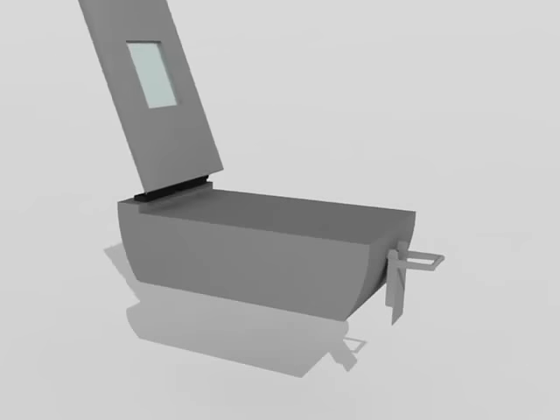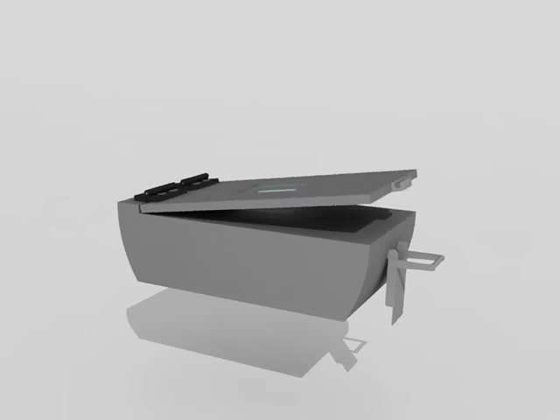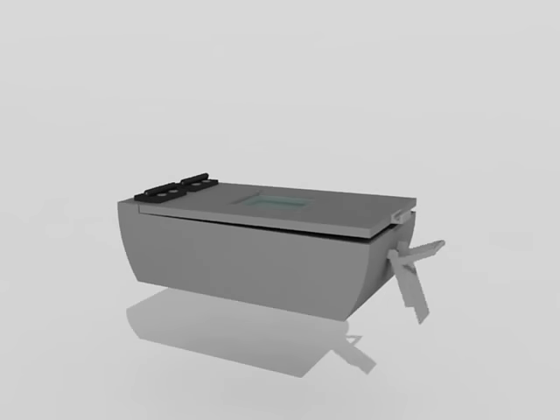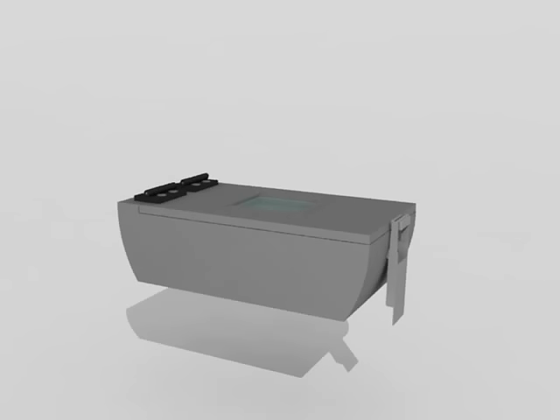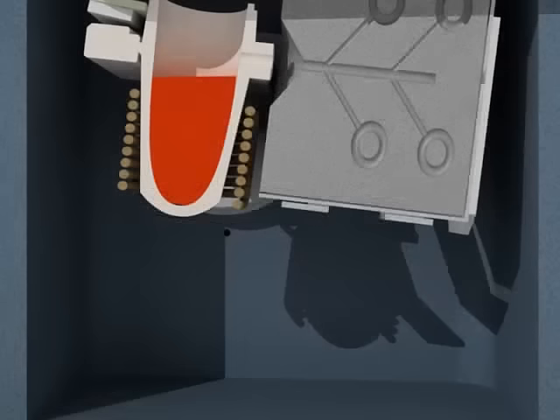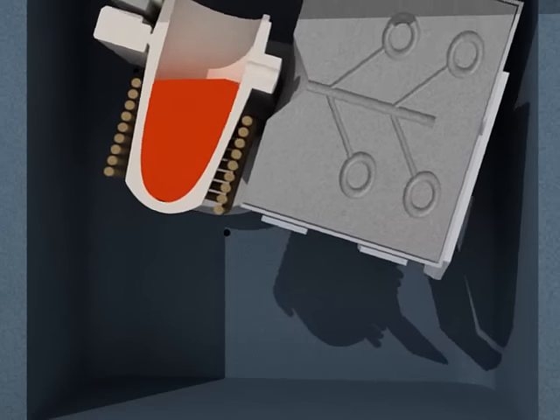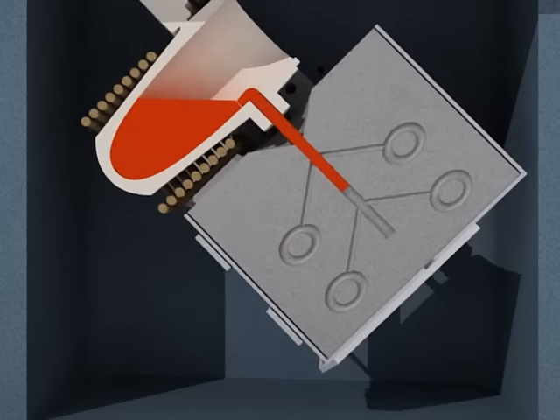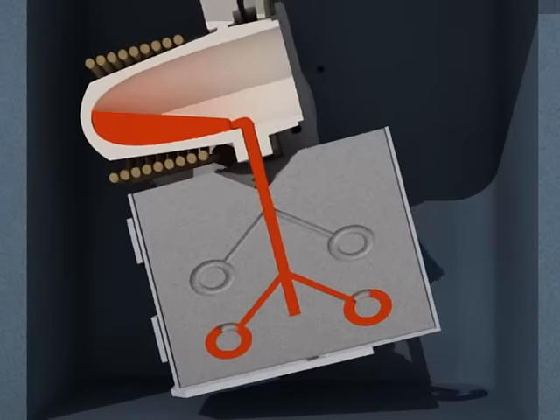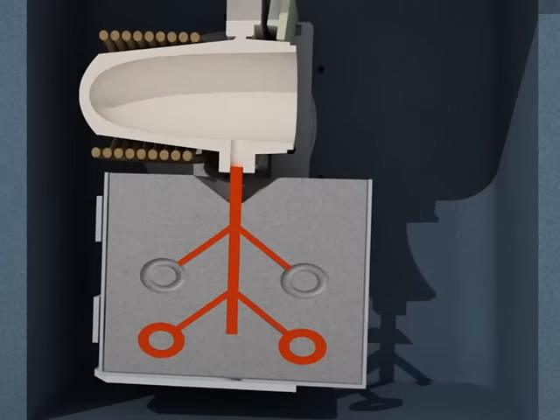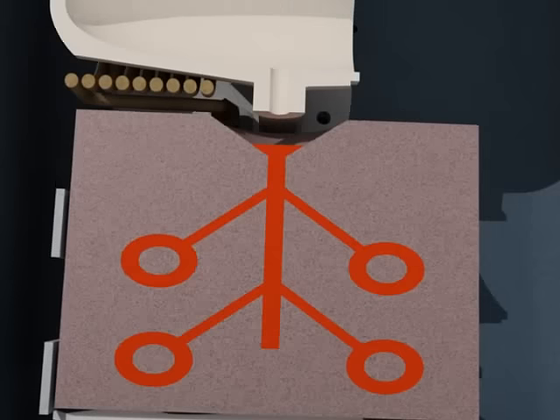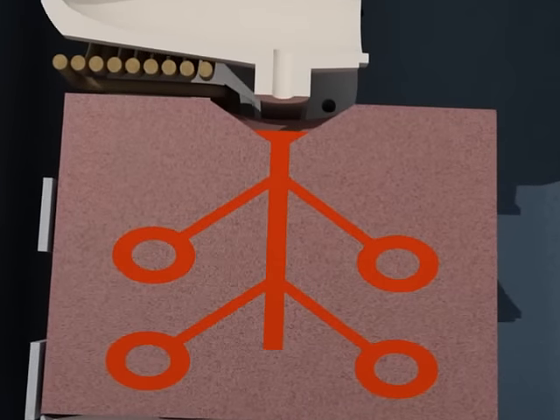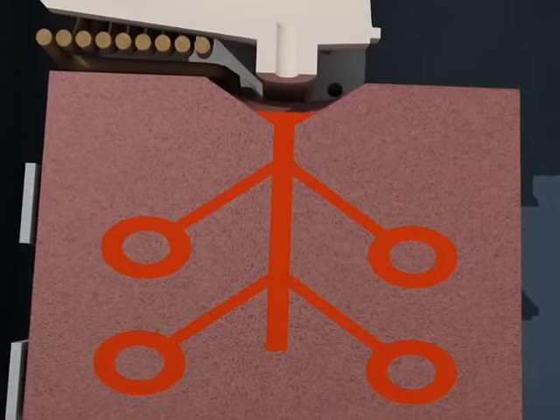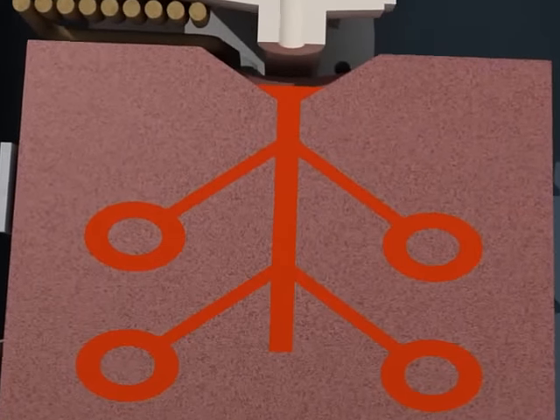In most of our competitors' machines, the metal cannot be effectively pressurized up to 4 bars since the machine structure is weak and gas pressure is slowly applied to the molten metal after pouring. This weak and slow overpressure leads to a raising of the temperature of both metal and flask in order to obtain a proper filling of the flask, with the obvious consequence that casting pieces will have porosity and a very rough surface due to the very high temperature.